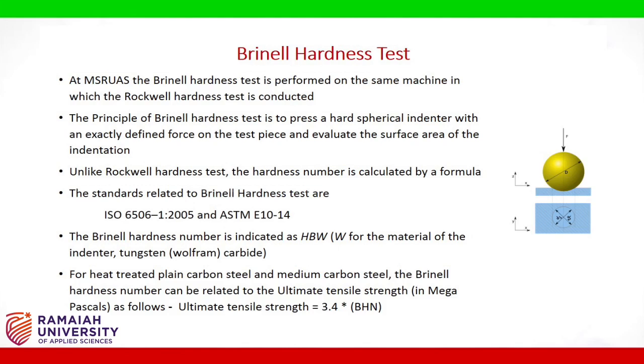The standards related to Brinell hardness test are ISO 6506-1:2005 and ASTM E10-14. The Brinell hardness number is indicated as HBW, W for the material of the indenter, tungsten, wolfram, carbide. For heat-treated plain carbon steel and medium carbon steel, the Brinell hardness number can be related to the ultimate tensile strength expressed in megapascals as follows. Ultimate tensile strength is equal to 3.4 times BHN.